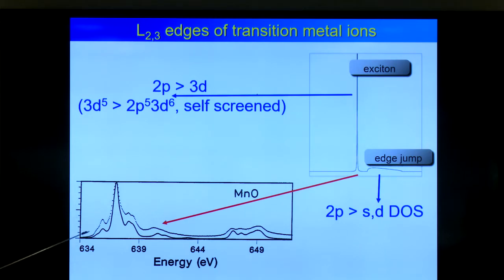And then I was at the conference and I saw this top spectrum and I thought, oh, that's nice, somebody else is doing the same calculations. But that was the first spectrum of the CT channel on the Dragon monochromator. And the agreement is really almost perfect. The difference is that the experimental spectrum is saturated, because even electron yield saturates on manganese oxide. So if you desaturate it, if you make this peak larger, you get an almost perfect calculation.